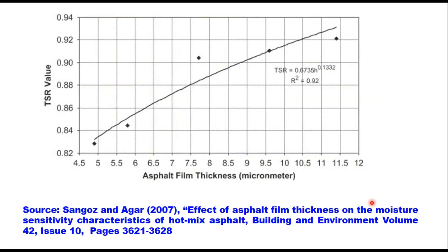Here is a figure taken from a research paper published in the Building and Environment journal. You can see that as asphalt film thickness increases, the TSR value — Tensile Strength Ratio — also increases. That is the indication of durability of the mixture, and it is one of the most important requirements in all mixes.